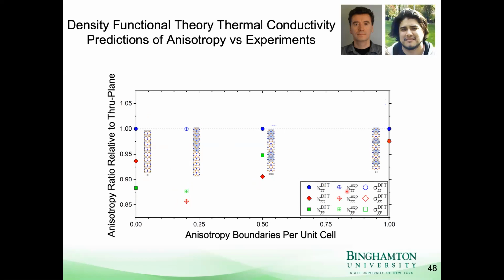So it's quite interesting. The only prior transport measurement that's been done on copper 3 tin was liquid phase epitaxy, and that has a very fast cooling rate. And our samples were annealed. So I think there might have been some microstructural difference that led to very high anisotropy for that prior measurement in the literature. But they didn't include any microstructure in their paper, so we couldn't really directly compare our properties to theirs.